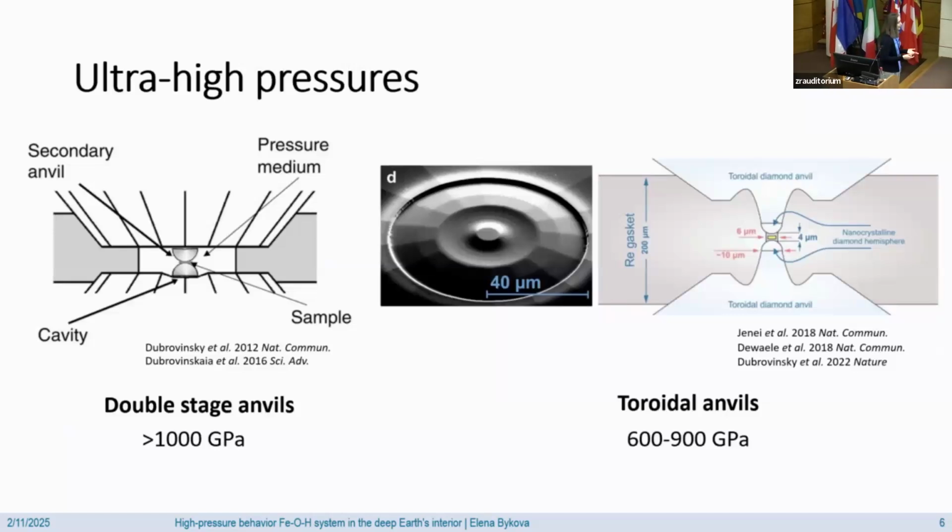If you want to go to way higher pressures, of course, you can decrease the area further by, for example, introducing secondary anvils. Those are half spheres, where these half spheres touch, and between them there is a miniature sample. And here in the submicron area, you can develop pressure up to 1 terapascal. Of course, this requires very huge dedication from the person in assembling those, and this is kind of a one-time experiment in a lifetime, because you don't want to do this for a second time.